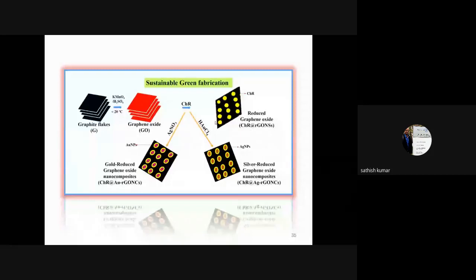And here, for the synthesis of reduced graphene oxide, we have to prepare the graphene oxide from the pristine graphite, which means the raw graphite flakes will be oxidized to graphene oxide. Then the graphene oxide will be used as the precursor for the synthesis of reduced graphene oxide. Here we will use chrysin as a reducing agent to reduce graphene oxide into reduced graphene oxide. Here you can see the multi-layer graphite flakes will be oxidized to graphene oxide, and from the multi-layer graphene oxide, monolayer reduced graphene oxide will be synthesized using chrysin as a reducing agent.